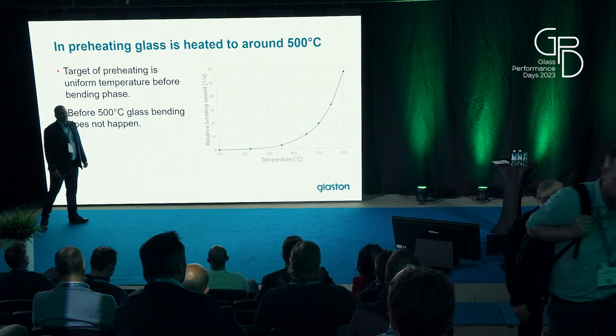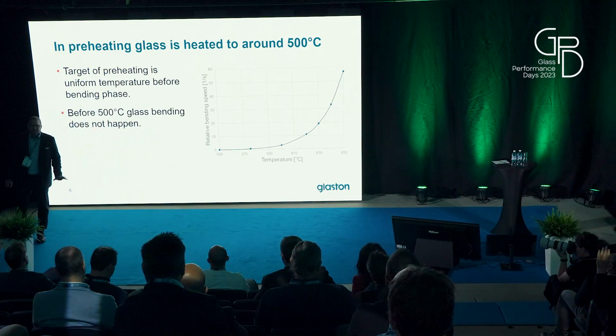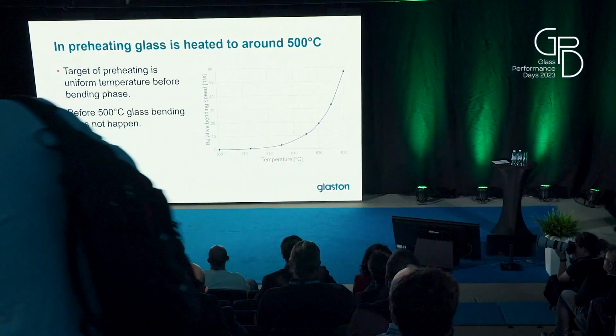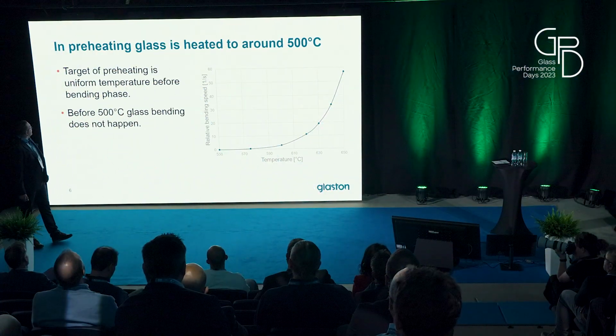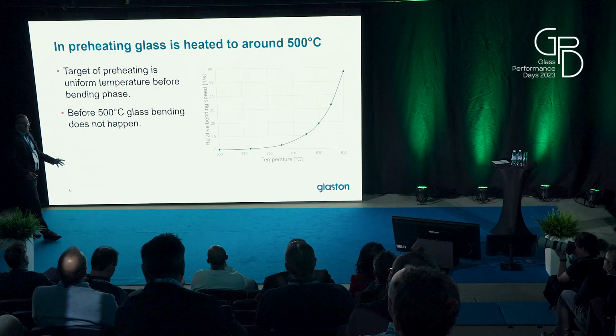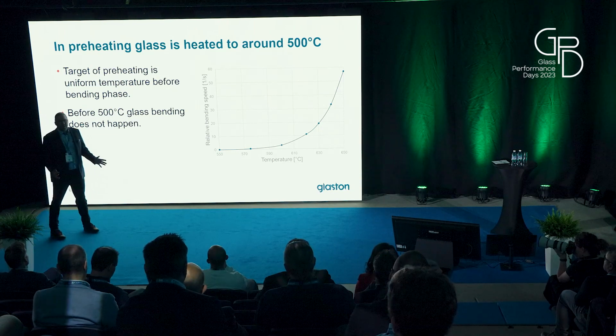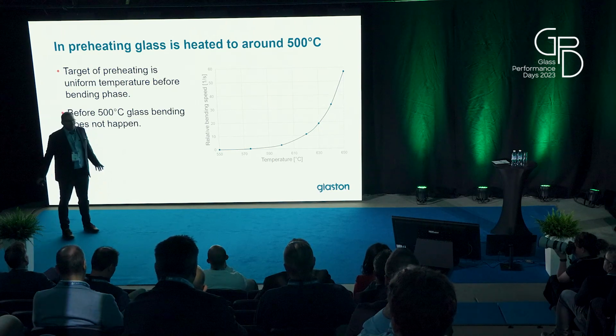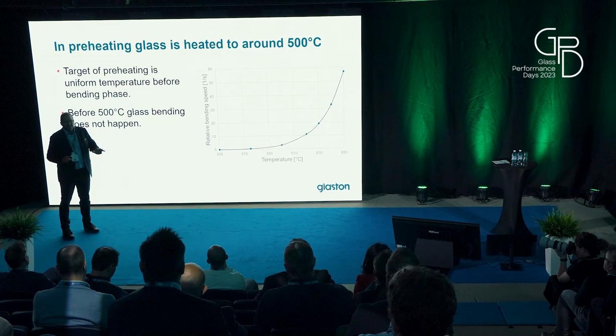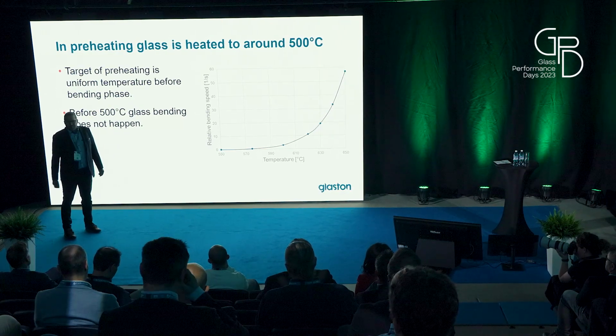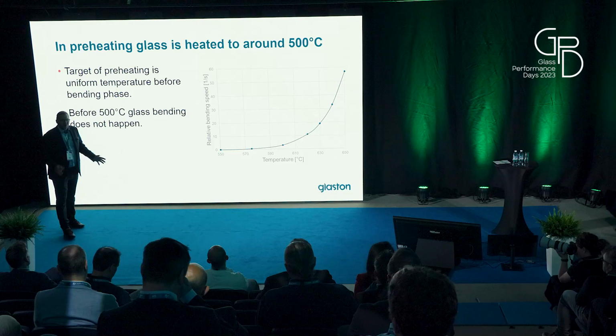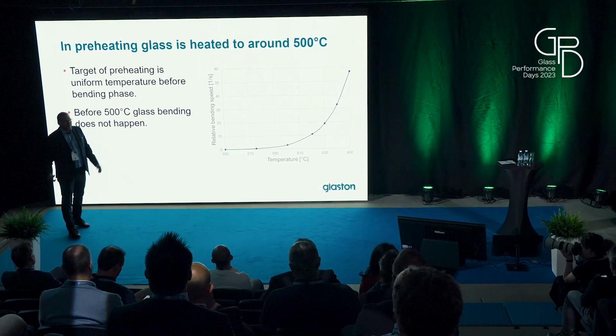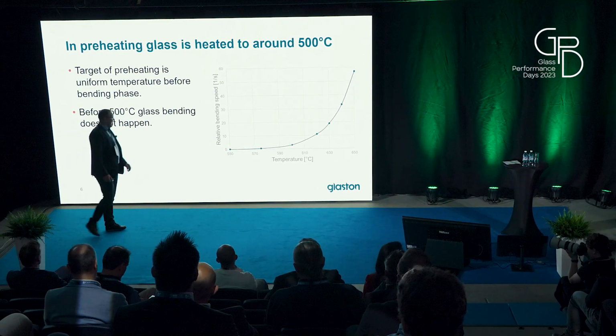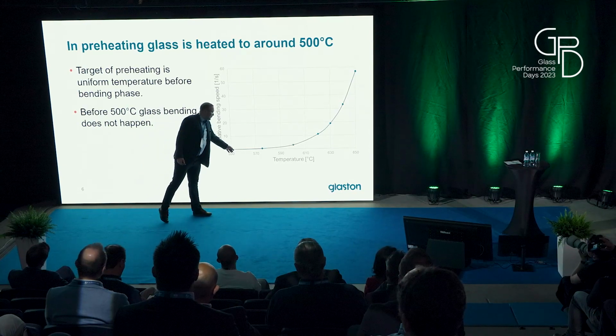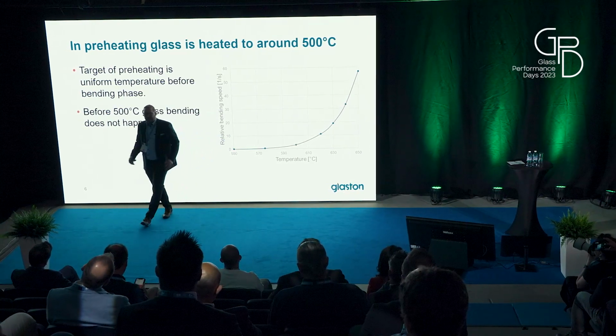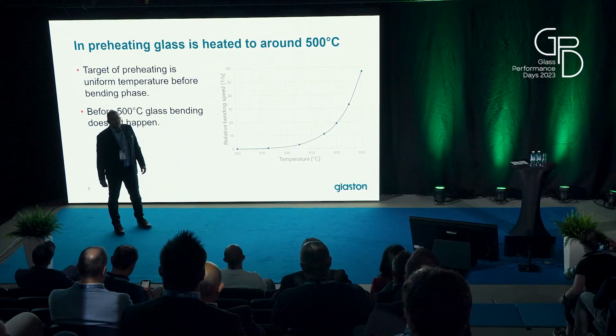So why is this 500 good in our mind? In preheating, we want to heat the glass up to 500 degrees. Glass is basically around 500 degrees plus minus 20 degrees. And then you can see that at that point, there isn't really bending speed for the glass.